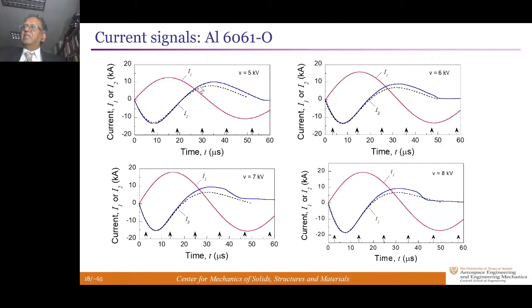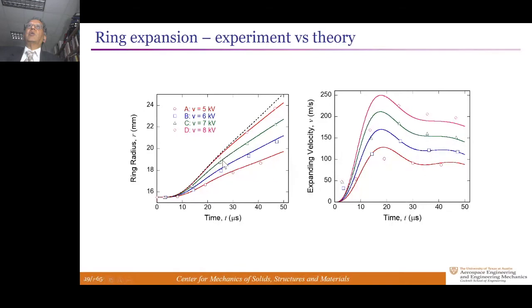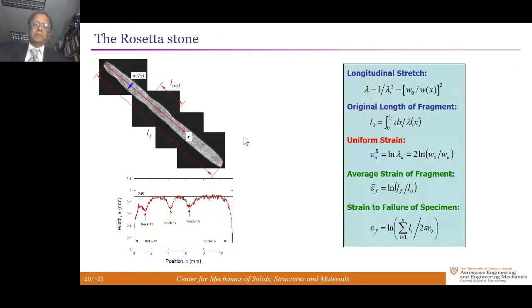So we can get a constitutive response of this thing until the onset of localization from here. You can also calculate the ring location or radius as a function of time, and this works even beyond the onset of localization, because beyond that it's just rigid body kinematics. But that's not the whole story.